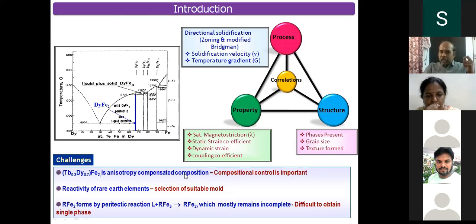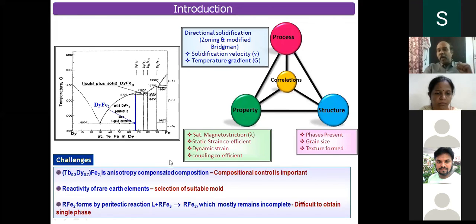So this material is also a challenging material to produce. The challenges are, first, composition control is very important, because if you see the phase diagram, it does not have any solubility. We have a very narrow solubility range. So composition control is very important. And one more thing is, this material is formed by a peritectic reaction. By peritectic reaction, I mean the liquid plus the RFe3 phase forms the RFe2 phase. So this peritectic reaction has to be suppressed somehow.